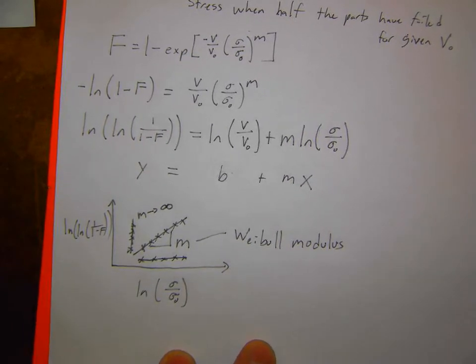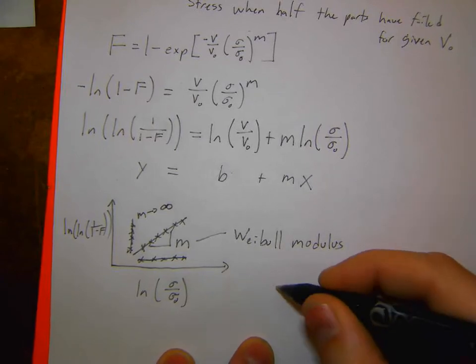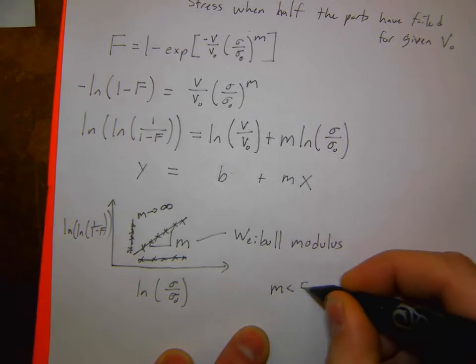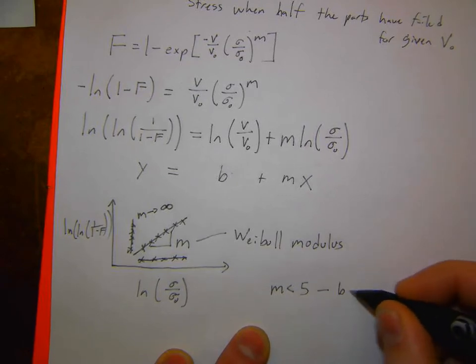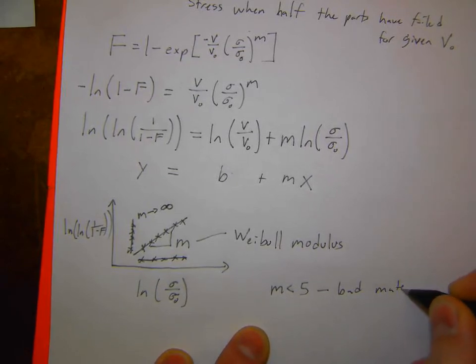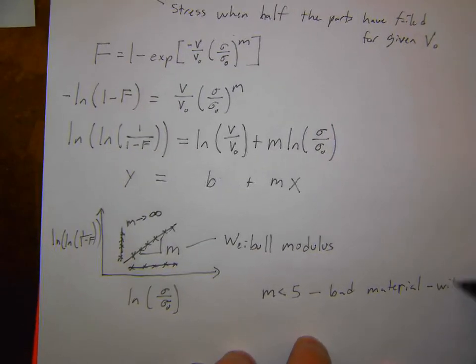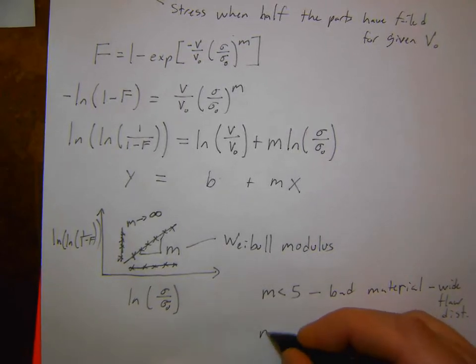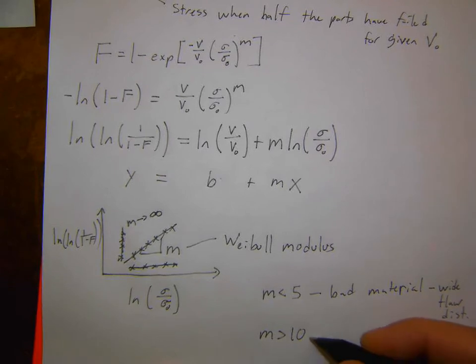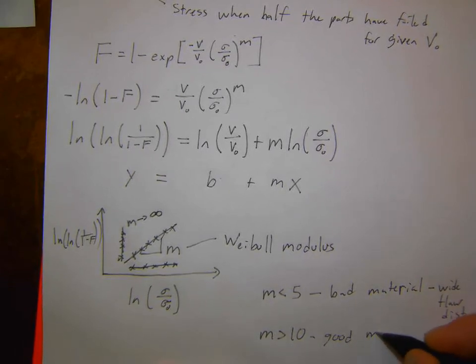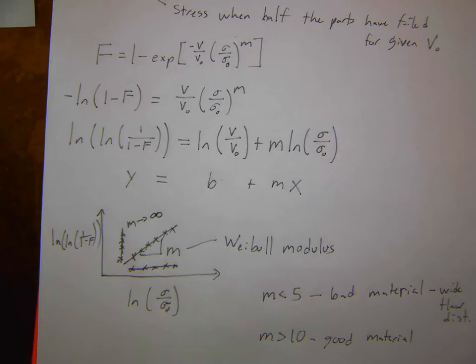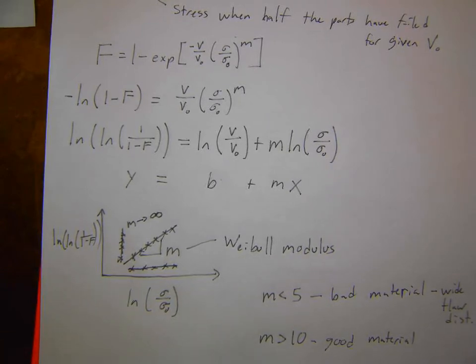Generally, in terms of actual numbers, if I have a Weibull modulus less than 5, this is kind of a bad material, or one with a wide distribution of flaws. And if I have an M that's greater than 10, this would be a good material with a more narrow distribution of flaws. And this distribution of flaws depends on both what the material is and the way that it's been processed.